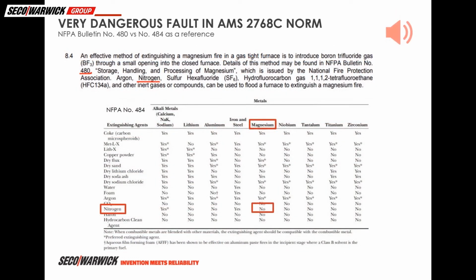After our research, studies and lab tests, we found that the AMS 2768C norm refers to NFPA bulletin number 480, which recommends the use of nitrogen as the extinguishing agent for magnesium fire. However, the NFPA replaced bulletin 480 with 484, in which nitrogen is not allowed as an extinguishing agent. This is a very significant change that has a huge impact on the safety of process in many production plants around the world.